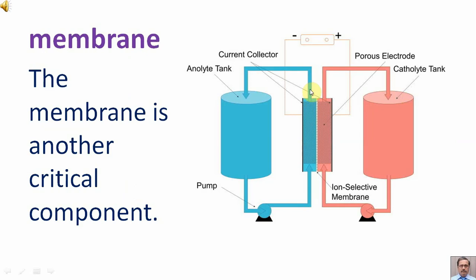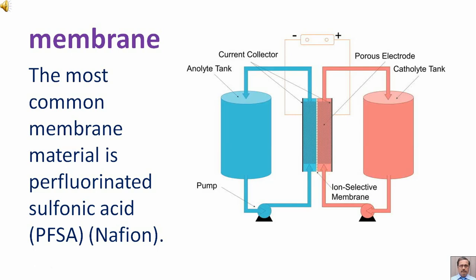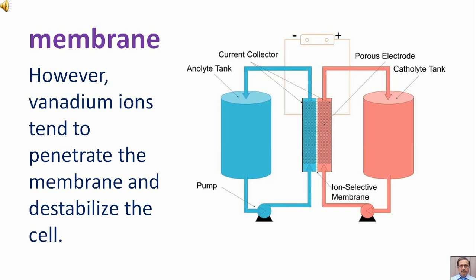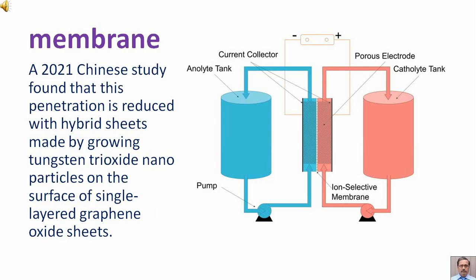Membrane is another critical component. The most common membrane material is perfluorinated sulfonic acid PFSA or Nafion. However, vanadium ions tend to penetrate the membrane and destabilize the cell. A 2021 Chinese study found that this penetration is reduced with hybrid sheets made by growing tungsten trioxide nanoparticles on the surface of single-layered graphene oxide sheets.